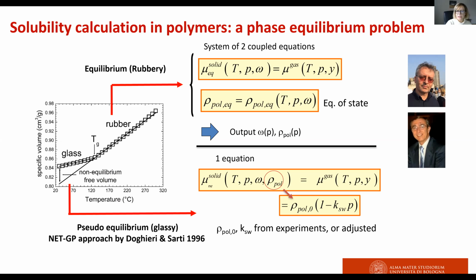In this case, you can still apply the phase equilibrium between the membrane and the gas phase, but the density has to be provided by correlations or by experiments, because the density of the glassy phase does not correspond to the equilibrium value calculated from an equation of state.